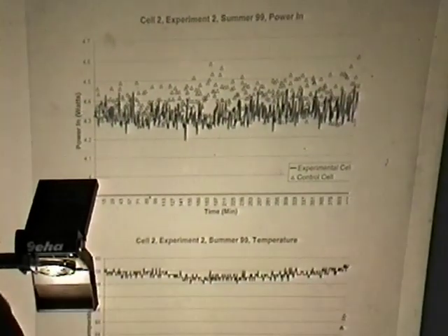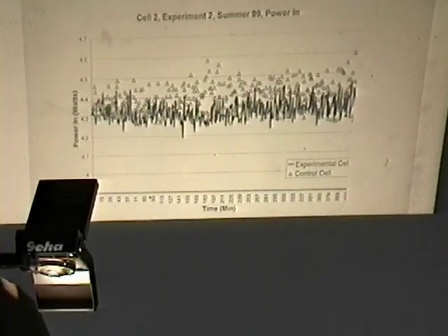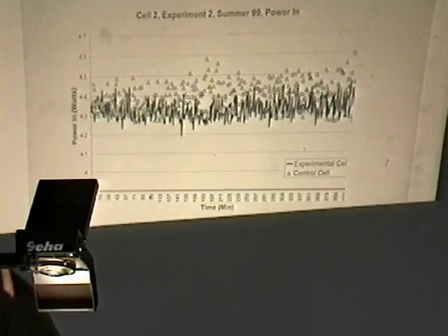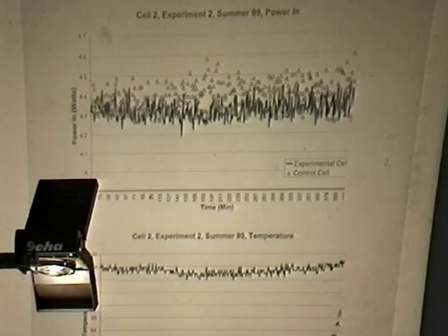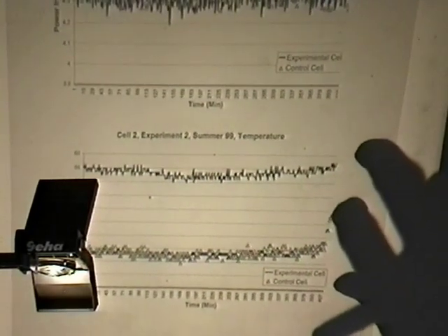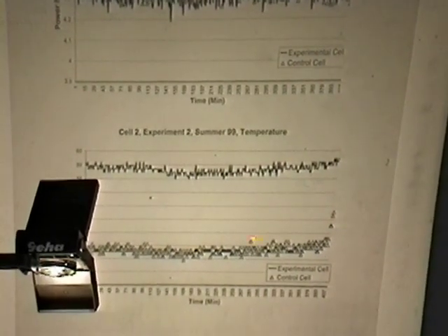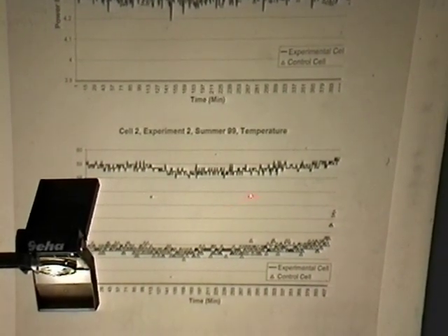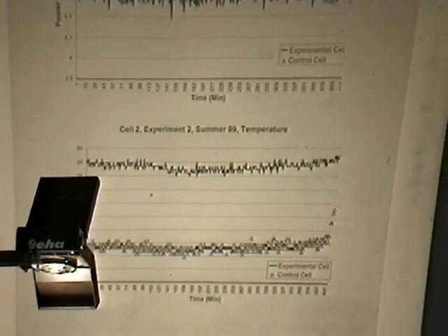Now, to put a face on this, during Cell 2, Experiment 2, you can see that the diamonds are the control cell and the line is the experimental cell. The power input to both of these were approximately the same. In fact, they were almost identical. However, the temperature output is very much different. The control cell is the bottom down here, and it's 6 degrees different from the experimental, where the power input was the same.